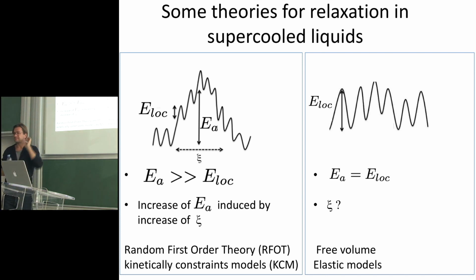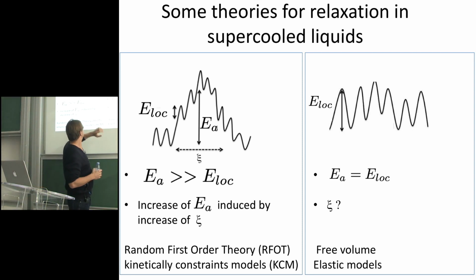So in some theories, actually it's easy to have local rearrangement of the particles. So you have some small barriers in the system. But what's really slowing you down is that to really relax, you need to break the system on some scale that grows. You need some cooperativity. So really in those models, the fact that the activation energy grows is very much related to the fact that I have some length scale that grows under cooling. And there are models that do that, and some can be very different. I mean, you have very different models that enter into this category, and I will just tell you that. And so for those models, it's very natural that the fact that the activation energy increases and that the dynamic is correlated comes hand in hand.